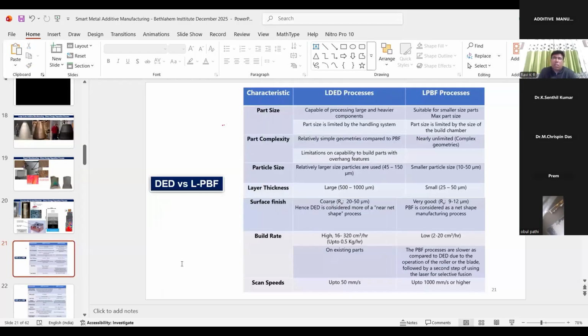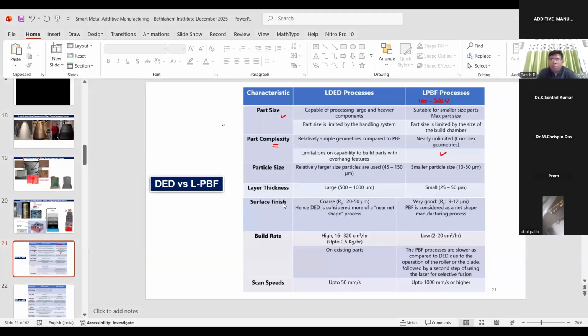Let me just restart this part. Sometimes it's a problem. I'll just explain meantime. In DED, we start with 500 watts. We go up to 3000 watts because you need slightly higher laser power. Obviously, with higher laser power and larger particle size, your surface finish would be poorer. On the other hand, one can print the part very fast.